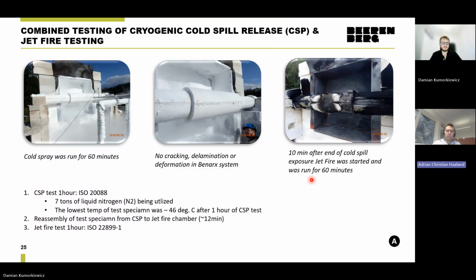These are some pictures for an example for a cryogenic and jet fire test. So as I mentioned earlier, first you subject the test specimen for an hour of liquid nitrogen jet. So you basically high pressure wash the specimen with a massive stream of liquid nitrogen. For this test, we used 7 tons of liquid nitrogen. So that's 2/3 of a full tanker truck. And after 1 hour of this frost inferno, it's going straight into the jet fire. And it has to withstand. It cannot fall apart or crack or delaminate. It has to prove integrity for the full fire duration. In this case, the jet fire test was run for 1 hour, but we've run for up to 3 hours of jet fire testing subsequent to 60 minutes of cryogenic.